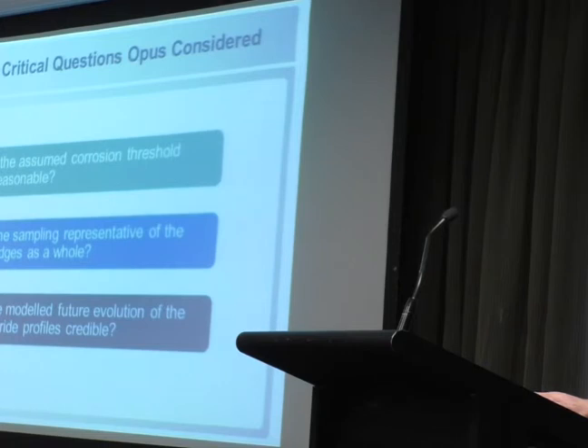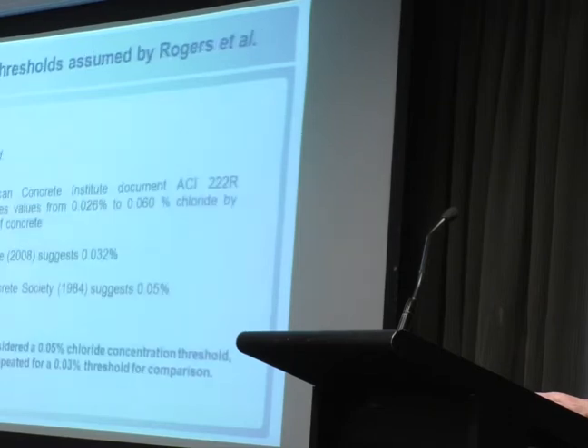One, is the assumed corrosion threshold reasonable? And you've already heard that there's a lot of debate about that. Two, was the sampling representative of the bridges as a whole? And three, is the modeled future evolution of the chloride profiles that Rhys presented credible? So Rhys assumed chloride concentrations of 0.03 and 0.05% chloride by mass of concrete as triggering corrosion.